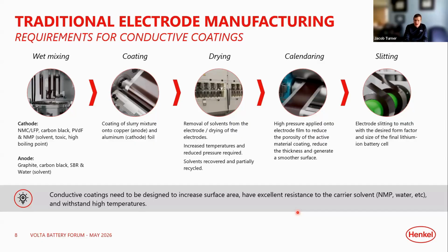It needs to withstand high temperatures depending on that solvent. So in the case of NMP, something like 200 degrees Celsius or so, as those materials or solvents are removed, our conductive coating needs to be able to withstand those conditions because we don't want any sort of degradation, and we want to have an expected performance once it's actually put inside of a cell.